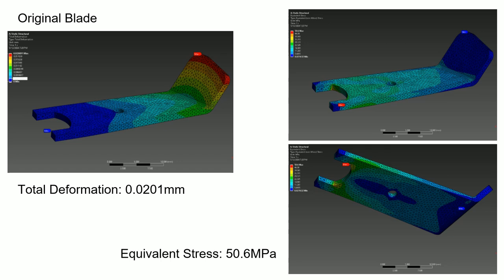The total deformation was 0.0201 millimeters, and the von Mises stress was 50.6 megapascals. In ANSYS, we probed the maximum and minimum locations of both the total displacement and von Mises stress. The maximum displacement of the original blade was at the very top of the blade. The maximum stress was on the bottom of the blade in the corner of the mating faces closest to the leading edge. These locations were to be expected.